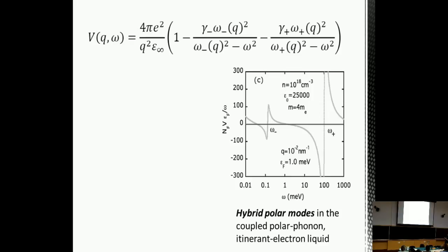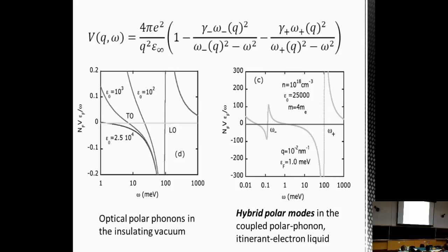If we go to the low doping limit of this interaction, so towards the insulating state, then these omega minus and omega plus become the transverse optical and longitudinal optical phonons. And if you go up to high doping, then they become the plasmons of the metal.